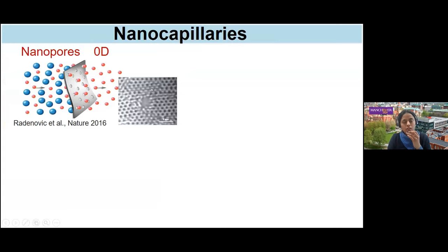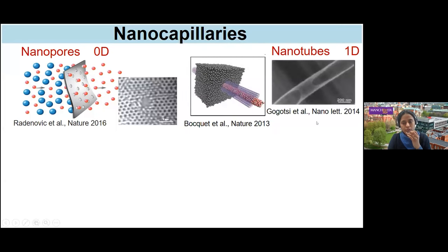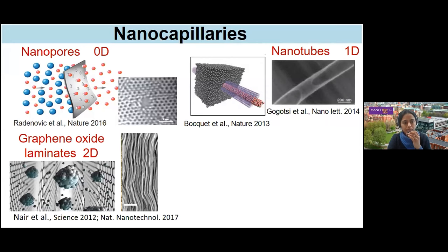There are many existing systems which can reach nanoscale and angstrom-scale dimensions. Categorizing them by dimensionality: first, the simplest are zero-dimensional nanopores — pores punched through a 2D material or conventional membrane, reaching a few nanometers to tens of angstroms. Another well-known system is nanotubes, studied for more than two decades, used both to template materials and study molecular flow. A more recent system involves two-dimensional graphene oxide and related laminates, where the space between stacked 2D material layers can also serve as a capillary.